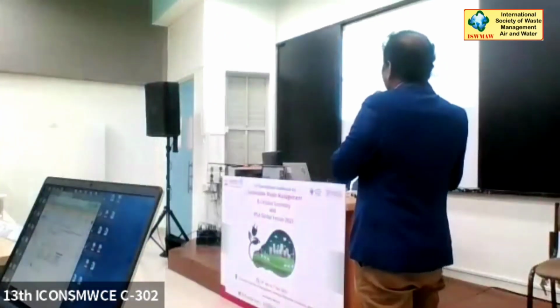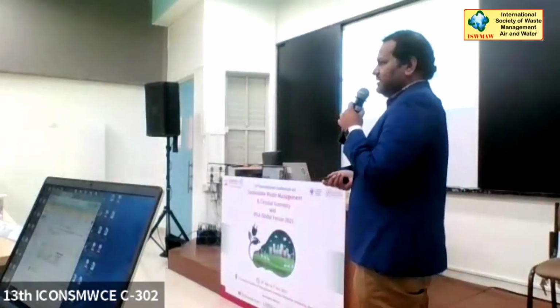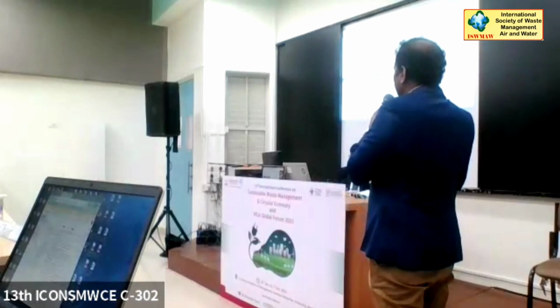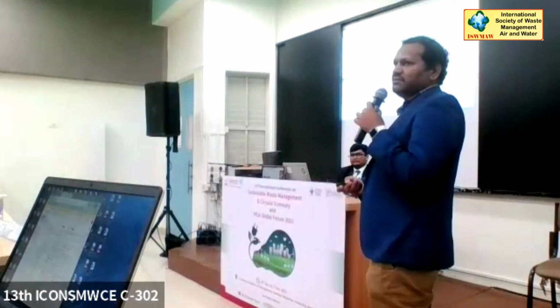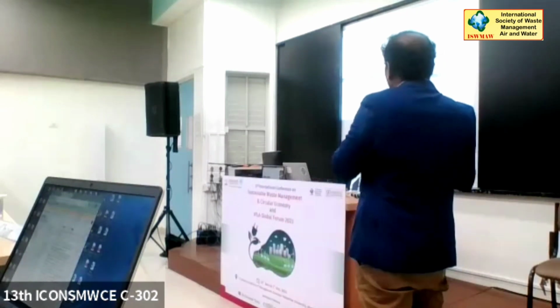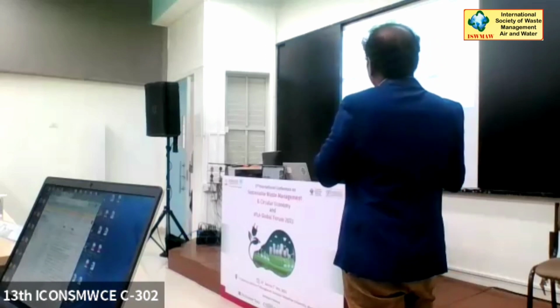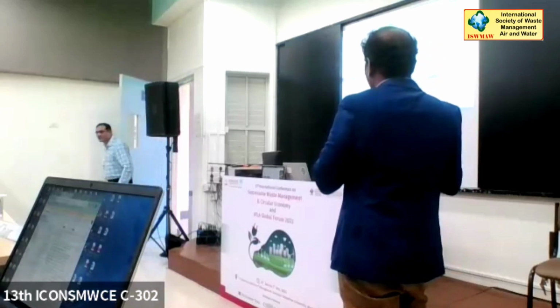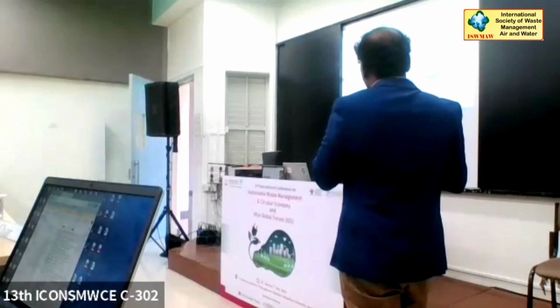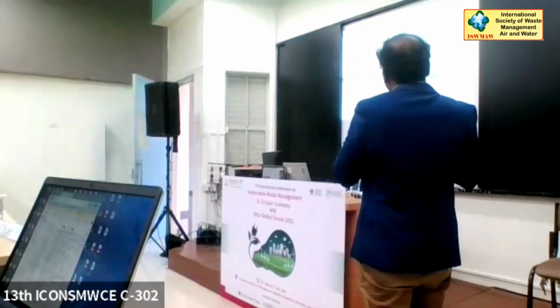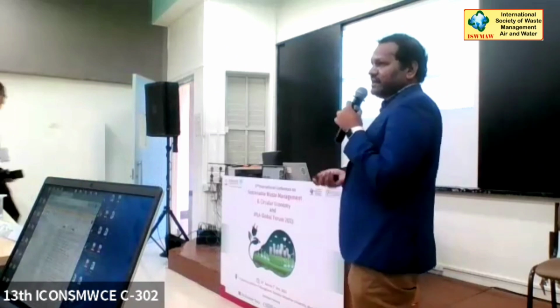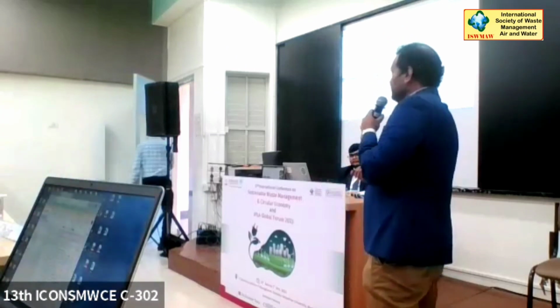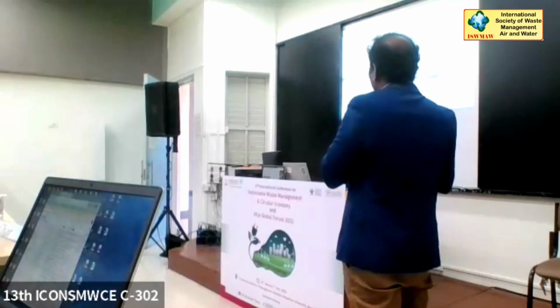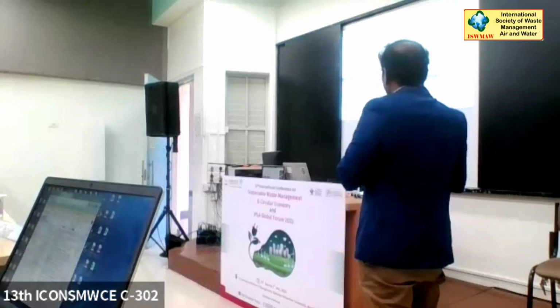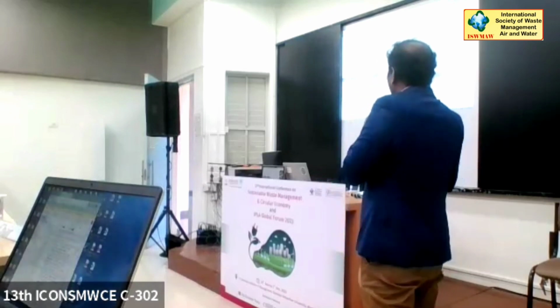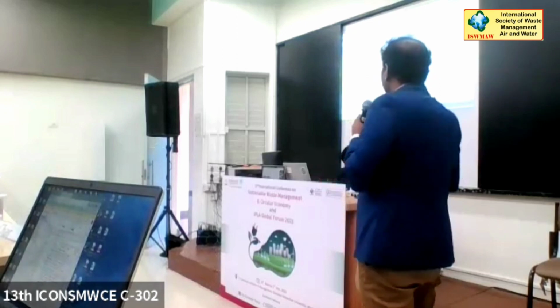So we have identified solid AFRs having less ash content, and then we have started utilizing them. Mostly these are the wastes we have identified at our end. Further, we have explored utilization of biomass with ash content more than 3%, and we are in the process of utilizing waste having higher ash content as well as higher iron content, because iron has a direct impact on the color of the cement. So this is the typical selection criteria for white cement.